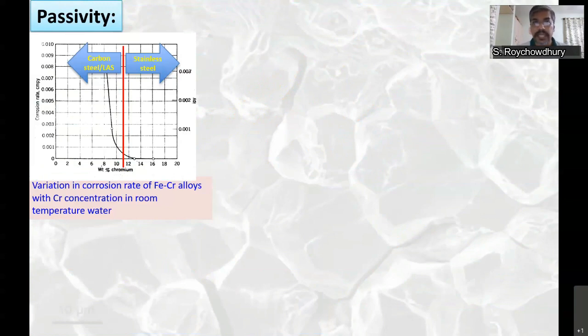I told you that alloying with chromium increases the resistance to corrosion. So if you see in this figure, the corrosion rate comes down with increase in chromium content, but around 11% you see there is a drastic reduction in the corrosion rate. So an iron alloy, a ferrous alloy containing a minimum of 11% chromium is called stainless steel, because it will not rust anymore.